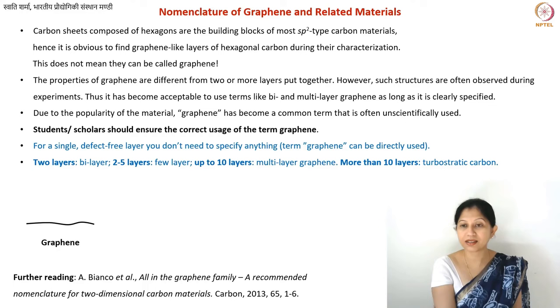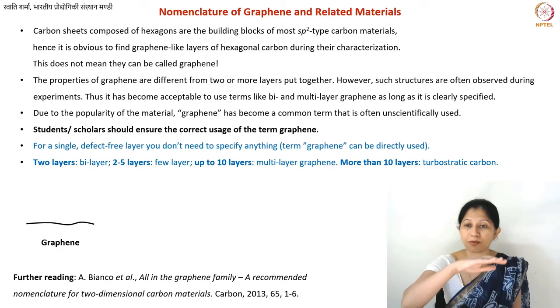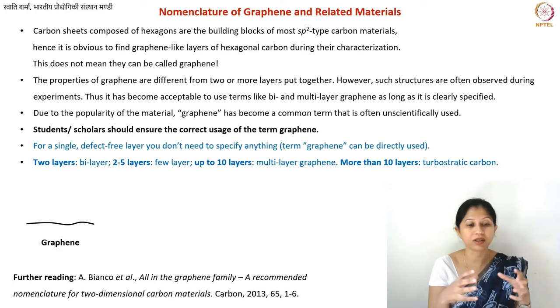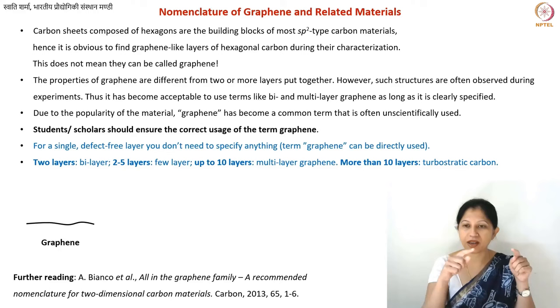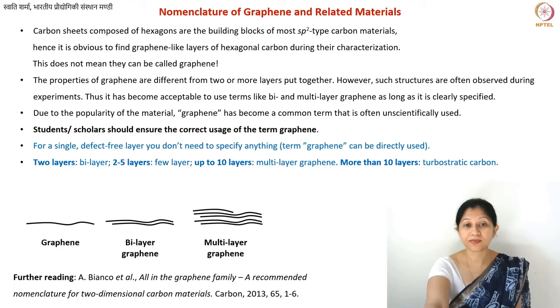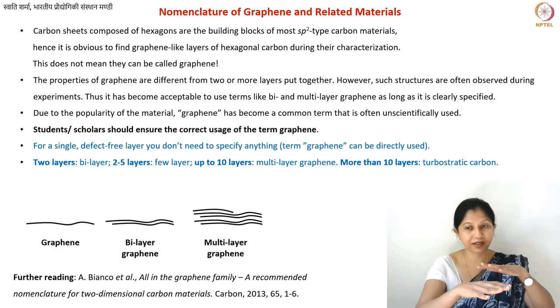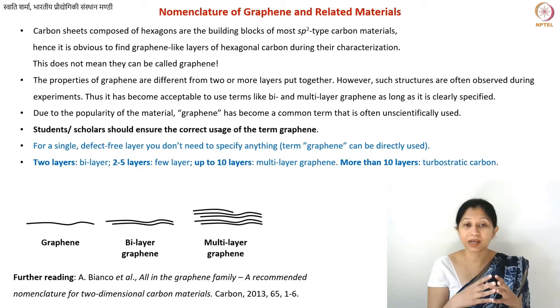Here I have shown it with some pictures. The first picture shows what you would call graphene — it's not a perfectly flat sheet; there is some natural waviness because the bonds are always vibrating. That waviness is not necessarily because of defects. When you have non-six-member rings, you get a stronger curvature. This waviness can be thermally annealed out. This is graphene, this is bilayer graphene, two layers, and multi-layer graphene — a layered structure that can be converted into graphite if annealed.